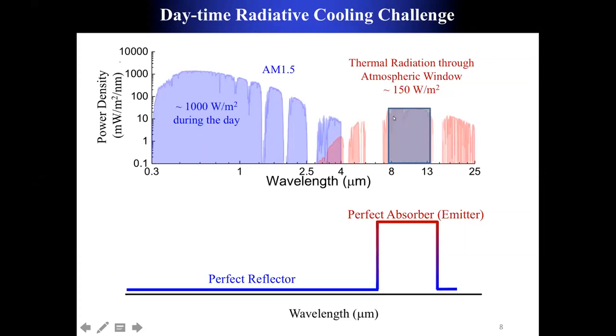Now, in the meantime, on the right-hand side, you see the roughly room temperature on the Earth and how the thermal radiation goes through the atmospheric window, or through the whole atmosphere, right? There is a particular part, from 8 to 13 micron wavelength electromagnetic wave, that can go directly through the atmosphere. It's called the atmospheric window, and you can have very good cooling there. Now, to make daytime, so-called sub-ambient cooling, the real challenge is to try to reflect all the sunlight. In the meantime, you want to make the emissivity as high as possible over that atmospheric window, and that's 8 to 13 micron wavelengths.